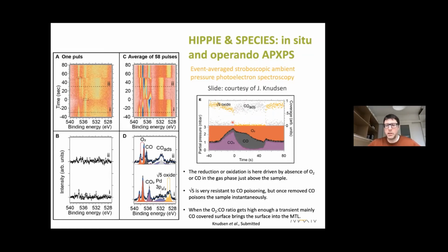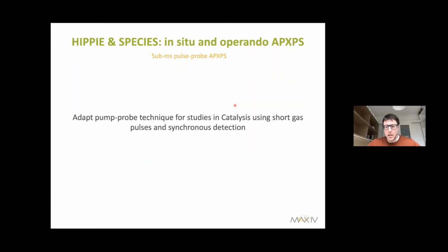However, one can go further down and see how exactly this conversion happens at the point where the metallic palladium starts, is still metallic. So you really need to focus on this range here and improve the time resolution to better than 130 milliseconds. For that, we need a slightly different setup.